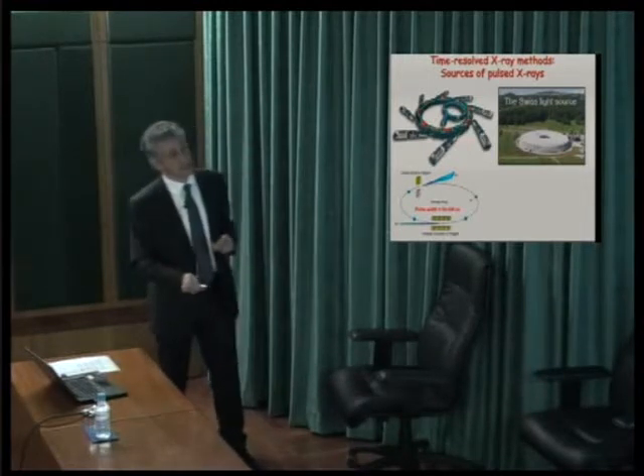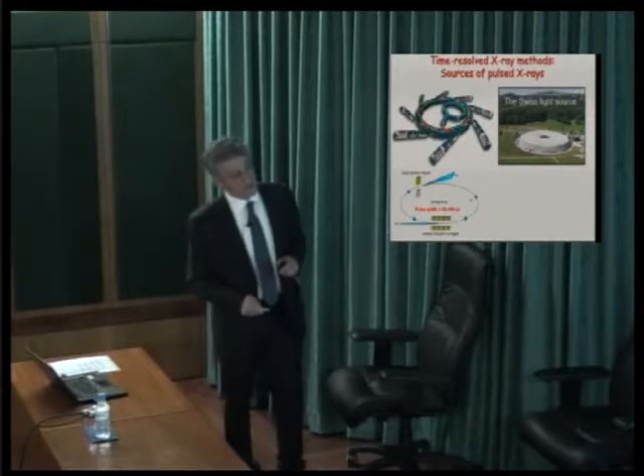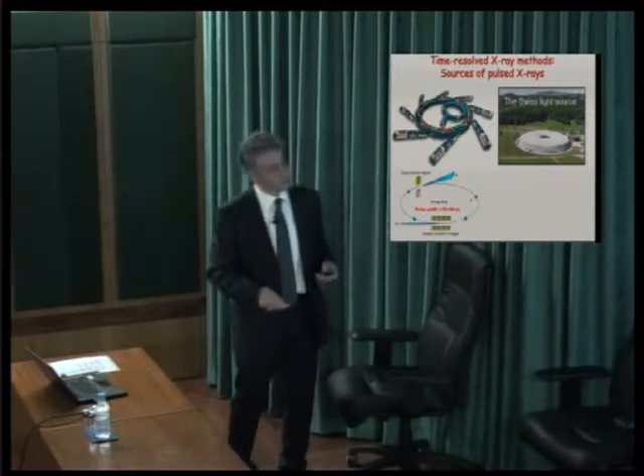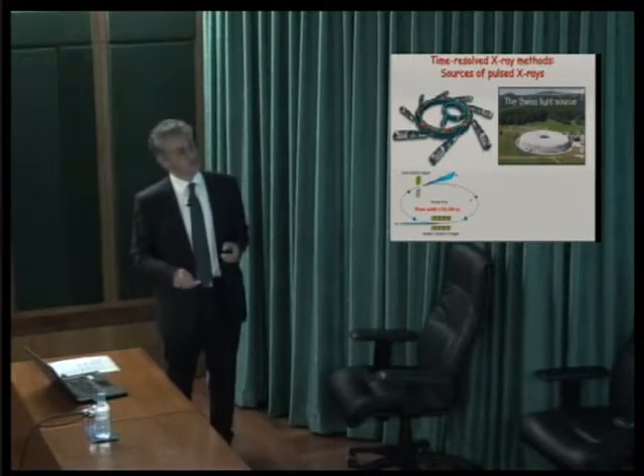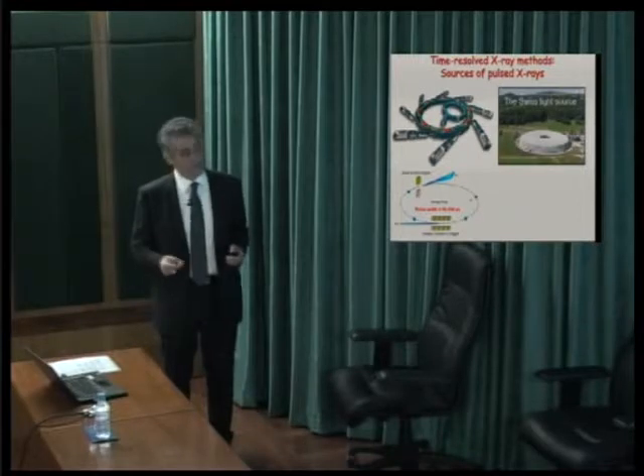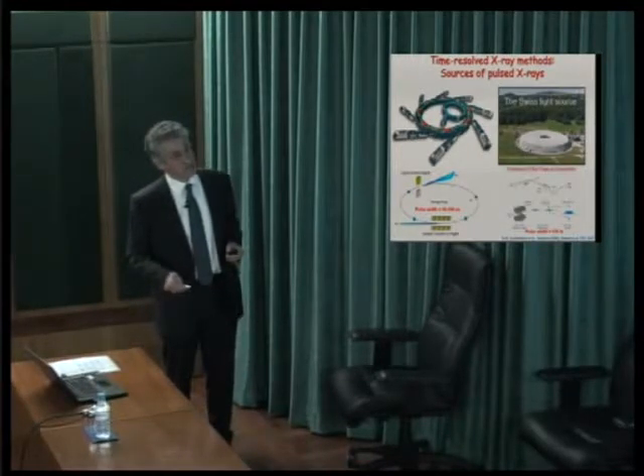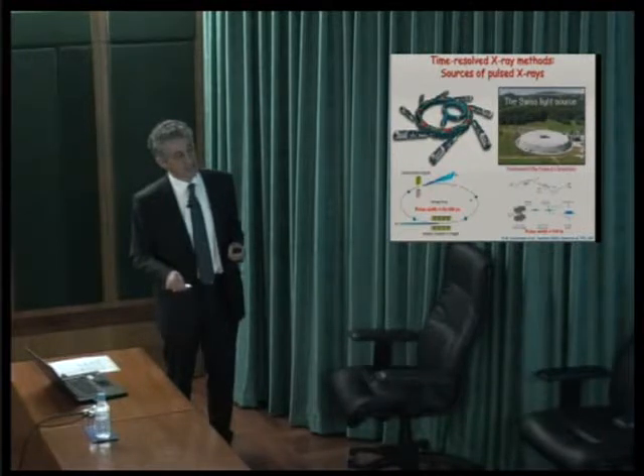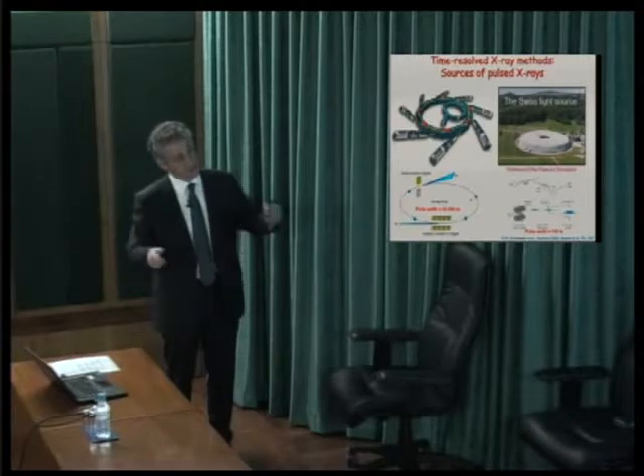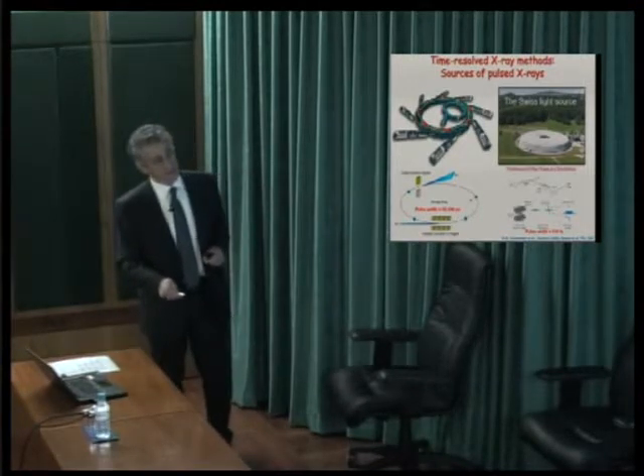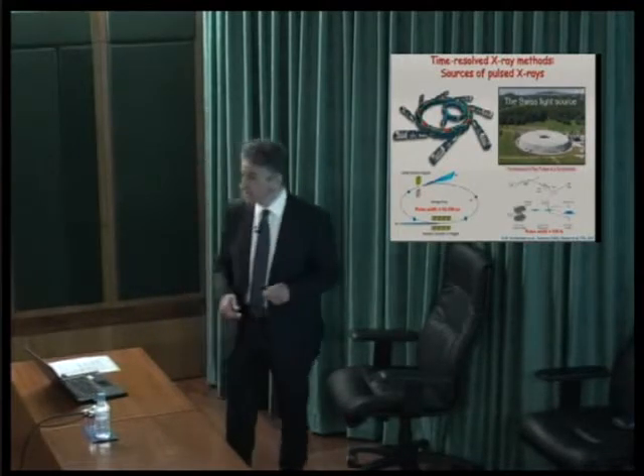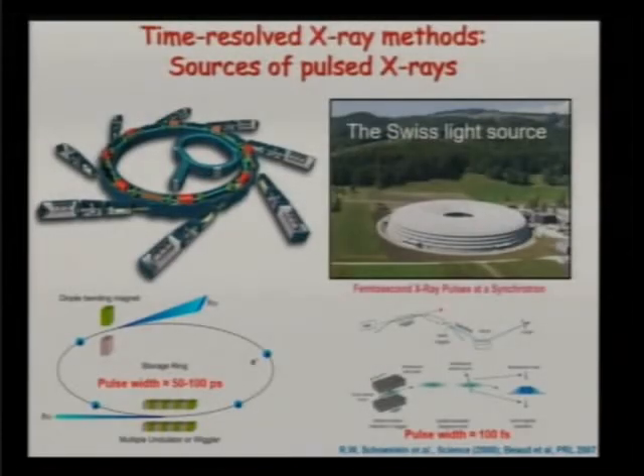By the way, you mentioned ALBA, you have ALBA in Barcelona. So this is still not in the time domain of nuclear motion, but we decided to move on and use whatever we could, and there is still a lot to do with this time resolution. Some years later, people could extract femtosecond duration pulses from synchrotrons by a scheme called the slicing scheme, which consists in co-propagating with the electron bunch, the cigar, an intense femtosecond laser pulse, and you slice out two wedges, and then when they go through the insertion devices, you get emission. But the problem with this technique is that if you slice a 100 picosecond pulse to a 100 femtosecond pulse, you already have a drop of 1,000 in the flux. So the flux is very weak. Nevertheless, we demonstrated the first X-ray spectroscopy experiment with this scheme, and that was quite a challenge then.